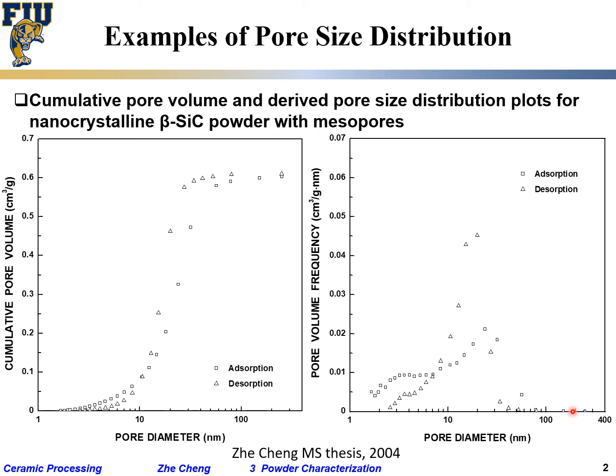Okay. So that just shows the majority of the pores within this material are roughly 10 to 20, 30 nanometer. And if you remember the SEM and TEM images, they correspond. The particles are 10 nanometer and the pores in between them are roughly 10 nanometer. Makes sense? Okay.